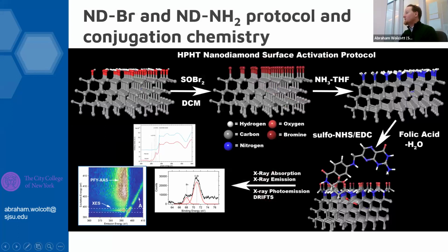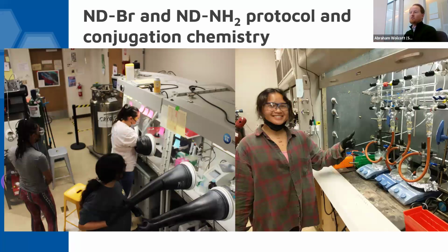In this particular case, we use folic acid. Why do we care about folic acid? Well, folate receptors are overexpressed in cancer cells. So if you wanted to confirm that you've done this conjugation, you could use a cancer cell line, a HeLa cell line, to be able to confirm that you have an increase in photoluminescence from your NVs. And of course, we use a series of different spectroscopic techniques to verify that our chemistry has worked: XAS, X-ray emission, and photoemission spectroscopies, as well as FTIR. A lot of this chemistry is done in air-free conditions, so we're in the glove box and on the Schlenk line quite often, and my researchers are there setting up those experiments.